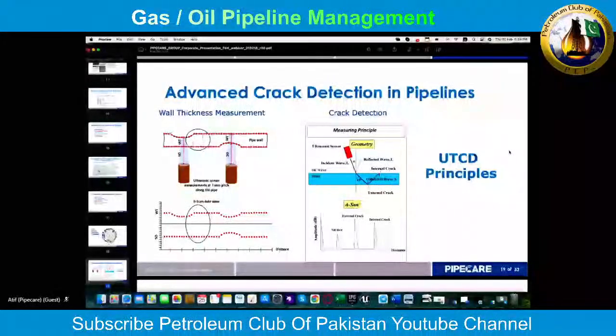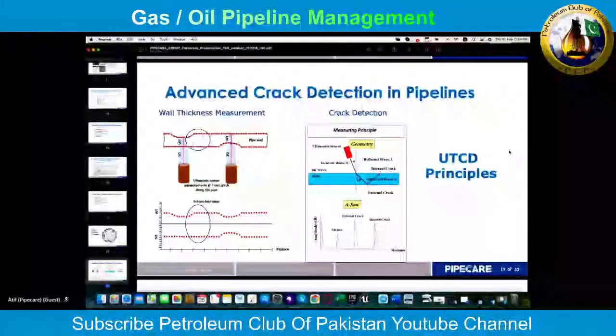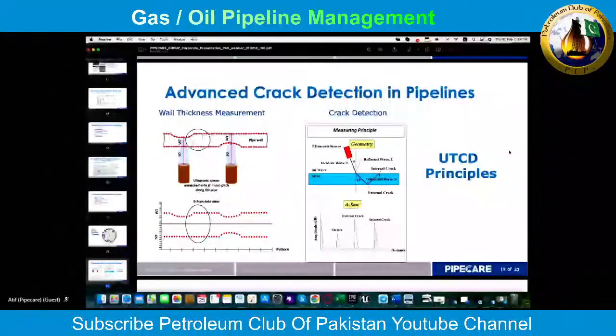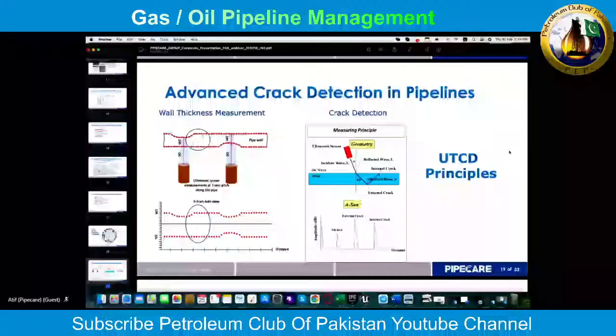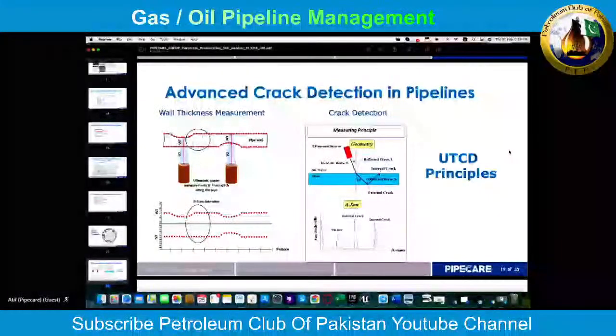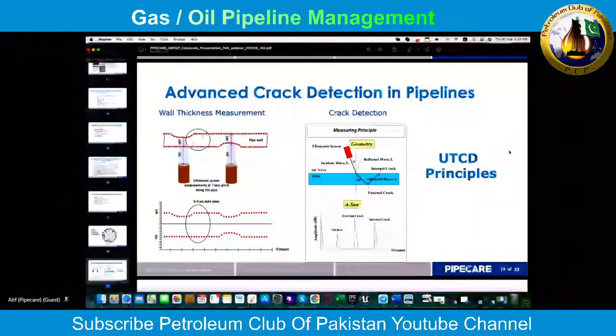And in order to overcome that, a new tool was developed which uses sensors or transducers which are mounted at an angle of between 15 and 17 degrees. And this results that when the ultrasound hits the internal pipe wall, it is deflected so that it travels at a 45-degree angle and therefore will return to the transducer if it hits a crack, as you can see on the picture.